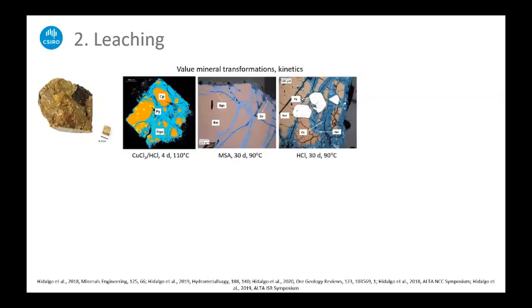And we were aiming to understand areas such as value mineral transformations and kinetics. So for example, if you start off with a chalcopyrite block, after a period of time, what does the chalcopyrite actually convert to? What is the sequence of mineral transformations that occur, and how long do they take? What sort of additional porosity or cracks are formed with volume changes? Tanya's work focused on deep hard rock deposits, and so that's why she looked at quite high temperatures for her work. We also looked at varying reagents, so for example, methane sulfonic acid and hydrochloric acid.